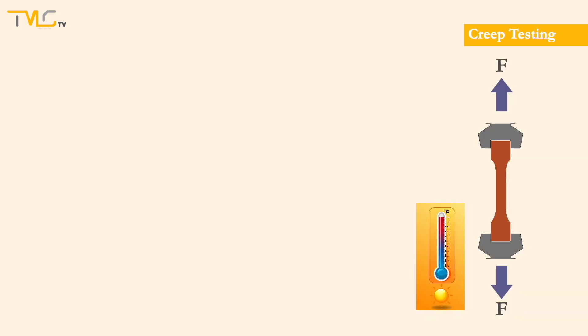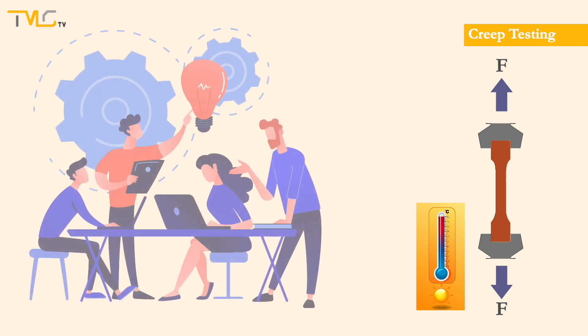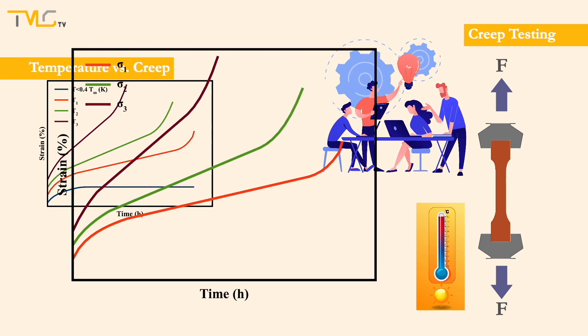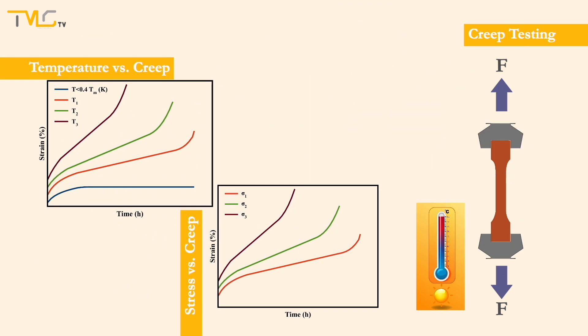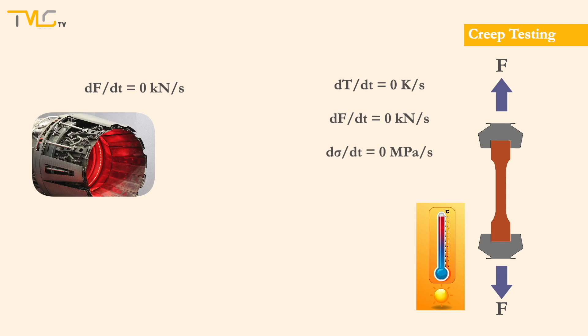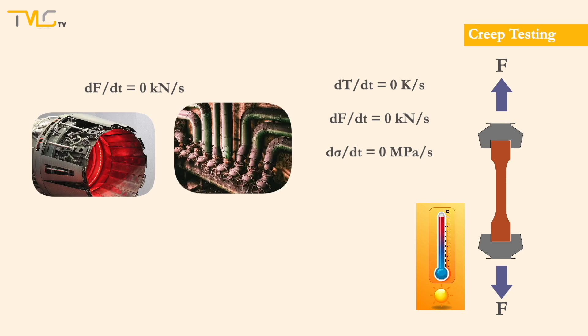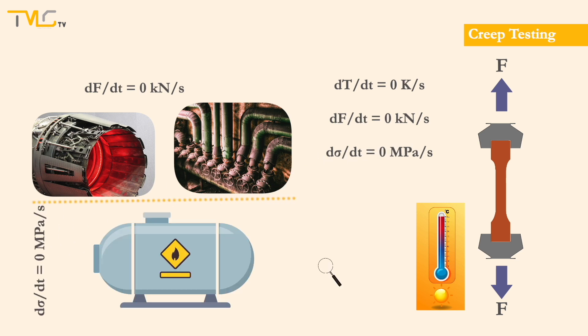After getting familiar with creep stages, now let's take a look at the creep testing, its details, and its interactions with experimental conditions. Creep tests are conducted at constant temperature, under constant loading, and sometimes under constant stress. Even though the constant load creep tests are more relevant to the conditions of daily applications, constant stress creep tests are sometimes performed to develop a deeper understanding of the fundamentals of the creep processes.